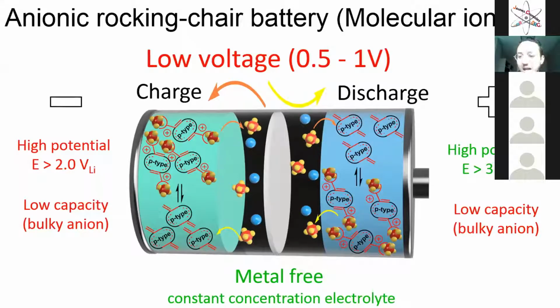The electrolyte would be cheap, and you can take advantage of the high potential of the cathode, because they are p-type based and they react at high potential. But the challenge is the negative electrode. Why? Because for the moment we have only one negative electrode that is suitable for this battery configuration, and it reacts at a relatively higher potential, higher than 2 volts. So the output voltage of this battery configuration will be low. Here we are talking about 0.5 to 1 volts, so it's very low. But it's a good direction if you really want to make a green battery that is metal free.